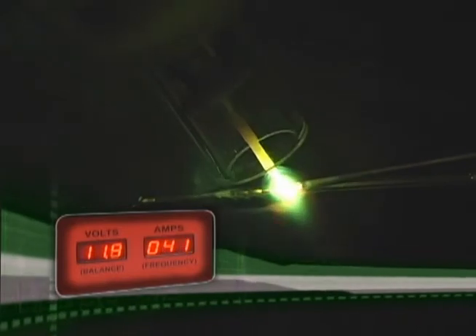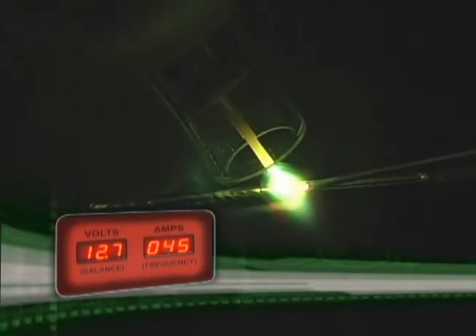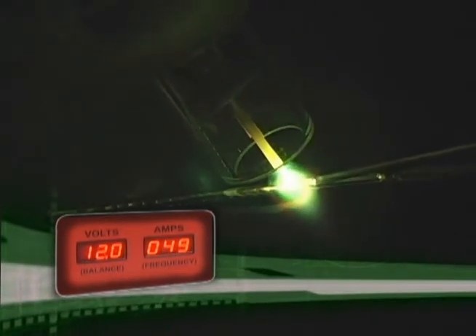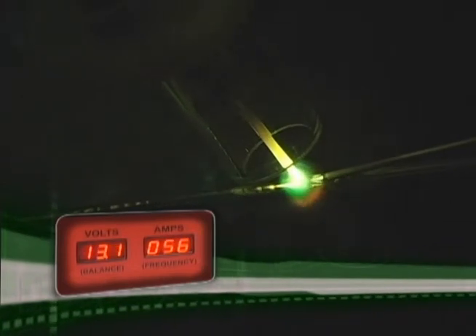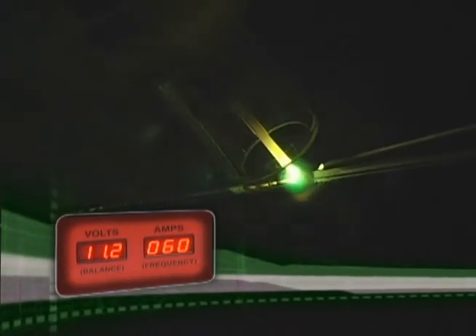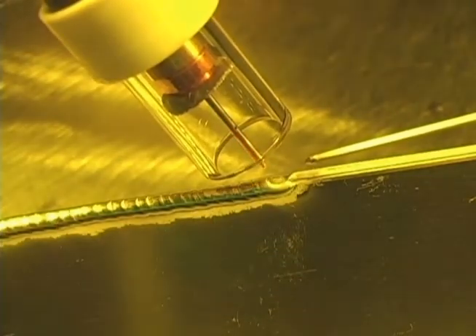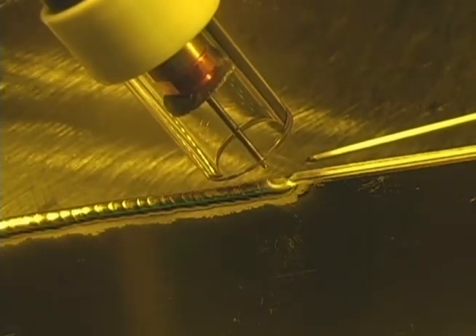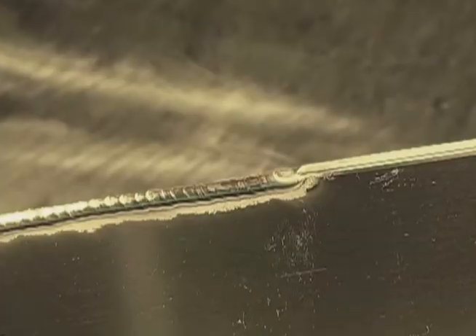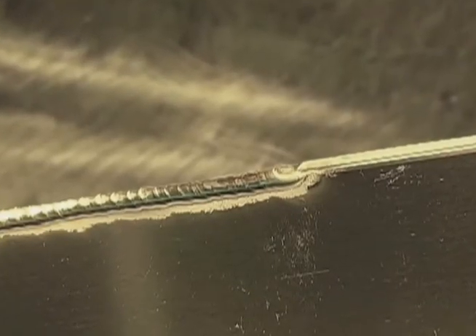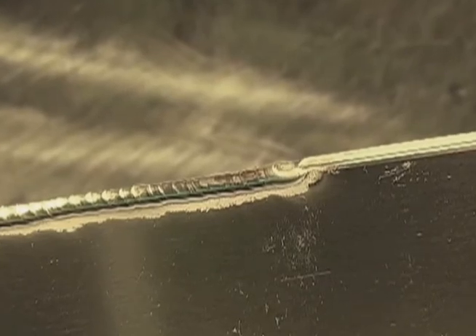In this specific application, we are able to lay the filler right in the crease and let the machine melt the filler and the two panels together. The machine automatically pulses between the welding current and the background current. The pulse frequency is set to 2 pulses per second. It really gives you a nice consistent bead appearance and minimizes heat input.